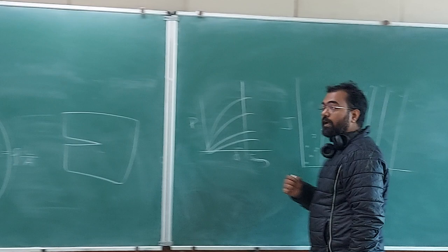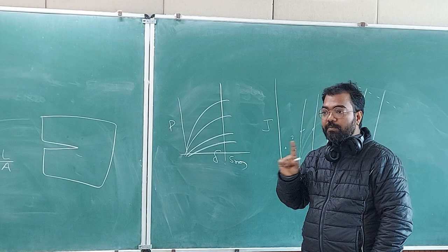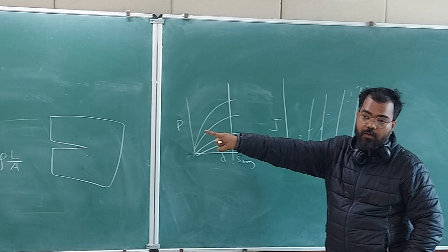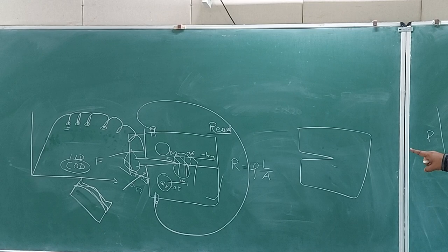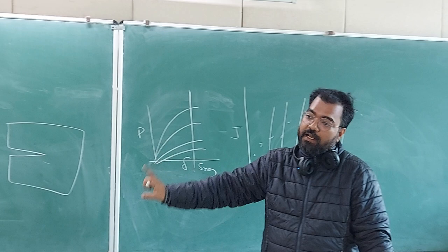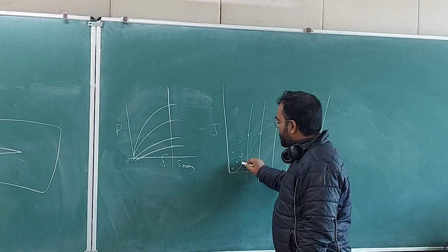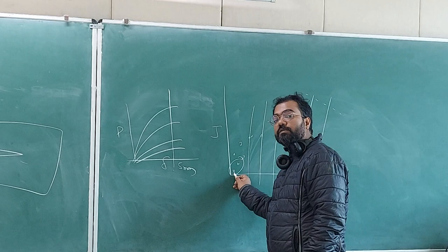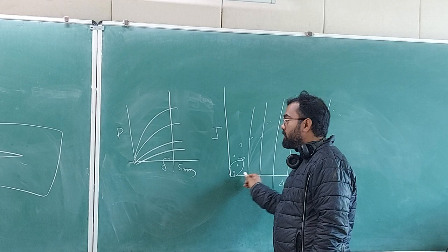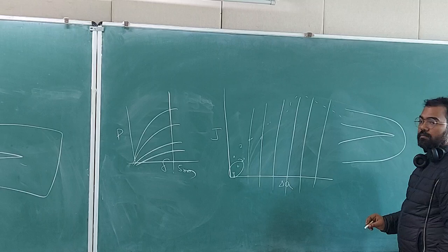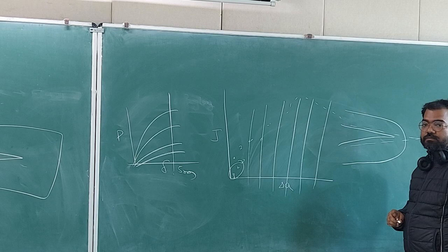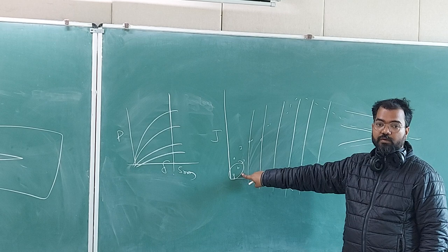I was also talking about how you will have some blunting, and that blunting is there in the load displacement curve. You cannot know whether the difference in the load displacement curve is because of blunting or because of real crack growth. So there will be some data which says you have some amount of crack growth that really is not crack growth, that is blunting. A sharp crack has just opened up, and this has caused a change in load displacement, and that is there in this data, and you don't know if that is real crack growth or blunting. So how to remove that, we will speak in the next class.